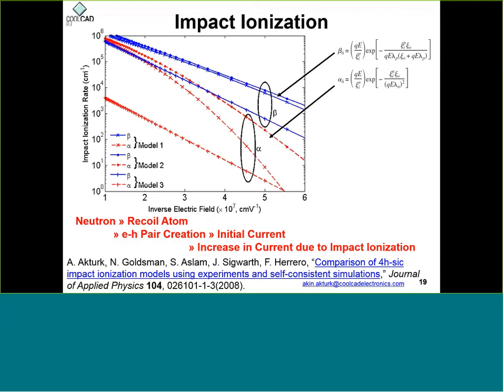And since this happens very quickly, generally within a few nanoseconds, you don't have time to remove this heat. So at these time scales, thermal constants like kappa or the thermal resistances do not have much meaning, because those are quantities that are applicable over long time periods, when all the optical and acoustic phonons can dissipate heat. Then we can see the effect of kappa or the thermal diffusion constant.